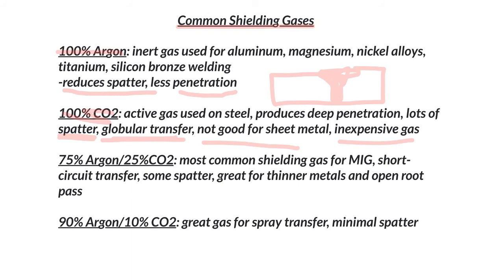Okay, so let's go to 75/25, probably the number one gas out there for MIG, short circuit transfer, some spatter, but if it's bad, you've got some setting issues going on, okay? So it's not the gas, it's your settings. Great for thin metals and also open root passes. We'll still use it on quarter inch or maybe even 3/8, and that's not a problem. We'll use it on half inch and stack beads, and that's fine. Remember, not everything has to be 100% penetration, through and through. That's not necessary. We're trying to hold metal together, and you'd be surprised how strong this stuff is.